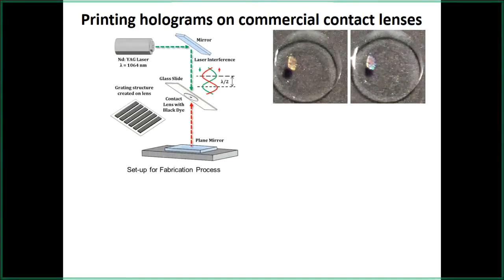It's a very fragile surface, which we attach to a glass slide. We let it dry. When it's dry, it sticks very well. It's mostly a hydrogel. Then we incorporated a dye on top of it, a small dot, and repeated the process. The process was a bit tricky because our dye got absorbed into the hydrogel, so we had to be careful of how thick our layer should be. Also, this was not a hard surface now, so the removal process was difficult. The material was not getting removed very easily, so a lot of optimization had to be done.